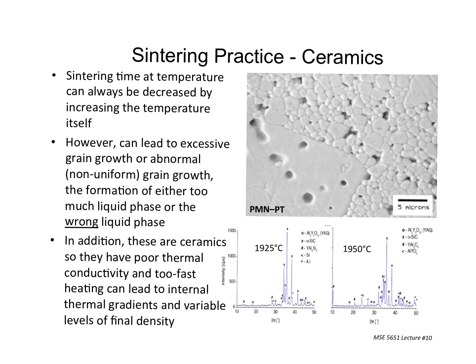And there's the other factor, in that we know that sintering time can always be decreased by increasing the temperature itself. So your boss says, hey, I don't like the fact that it takes 5 hours. We want it to take 1 hour. Well, let's crank it up by 200 degrees. And yeah, maybe it will take only an hour. But it can lead to excessive grain growth or abnormal grain growth.